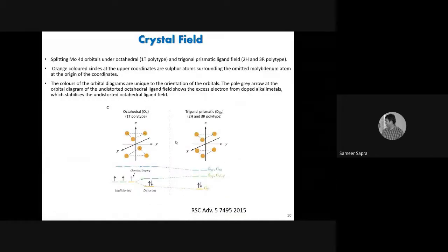So if you look at the coordination, it's explained on the basis of the crystal field stabilization energy. If you're looking at molybdenum 4+, then you have 2 d electrons. It's a d2 configuration. So if I put it in an octahedral field, then you have the very famous t2g-eg splitting, and you'll have only 2 electrons over here.